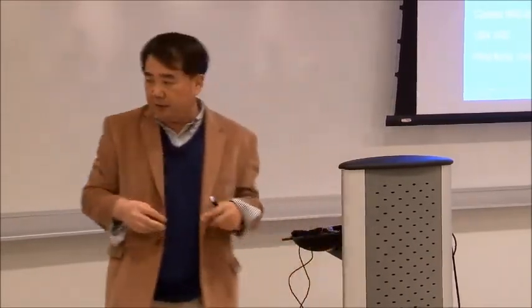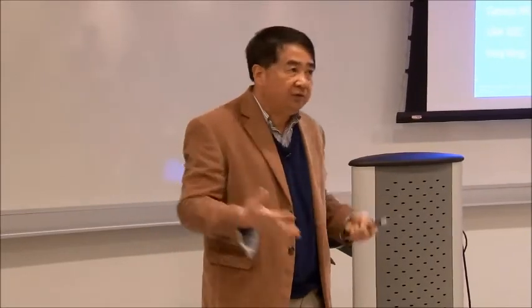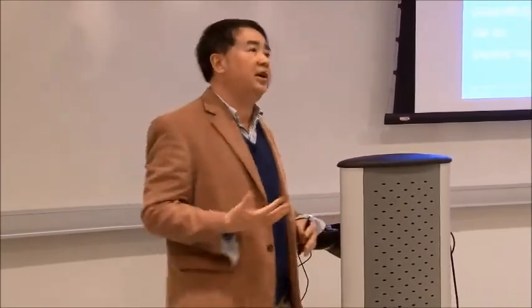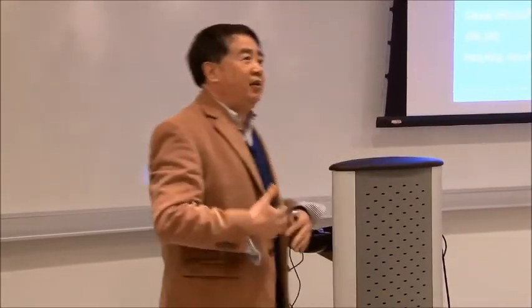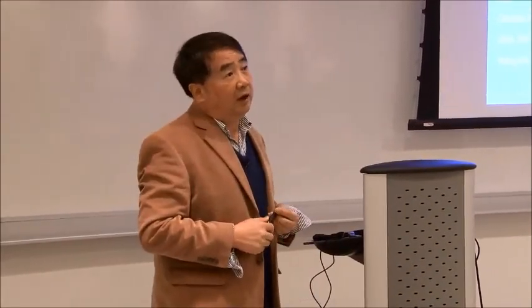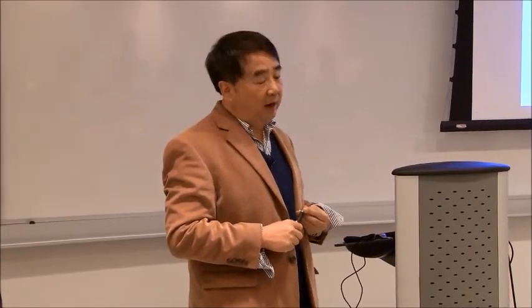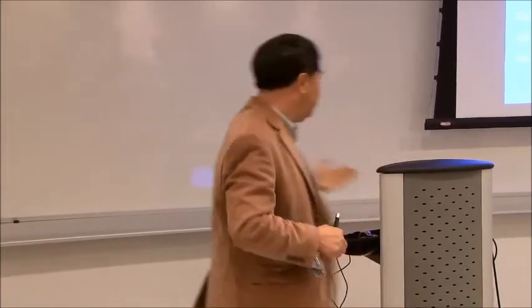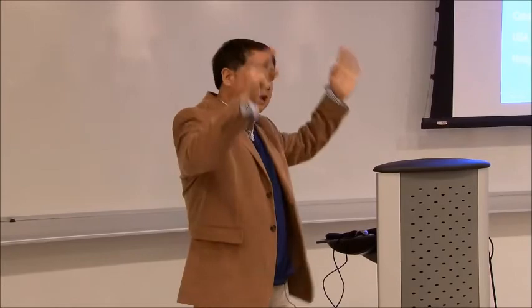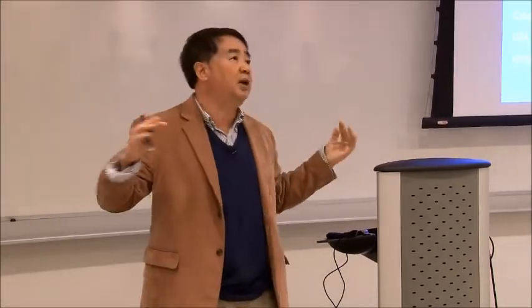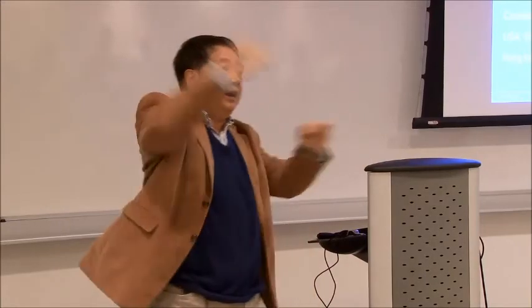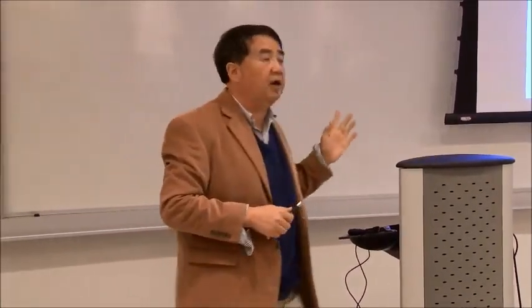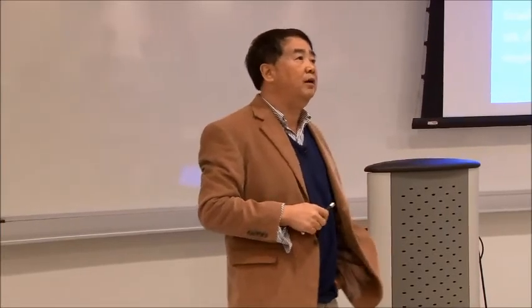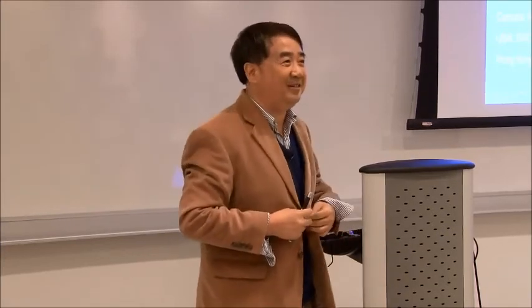But if you make a theoretical model where I put 30 atoms and 5 impurities in there, I'm not really having silicon anymore. This is a theoretical material where the chemistry changes so much that you might get different band gaps, and that will be reflected by your calculation, right? But if we do this, we will see a doping potential and so on, your Fermi level is changed, and you have that kind of physics, but you don't see this narrowing of the band gap because of the impurity concentration. I think in your case, maybe you have put in so many impurities that you should not call it silicon anymore, okay? Something like that, I guess. Yeah.